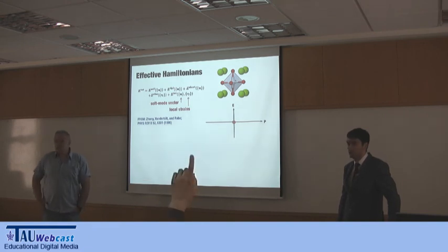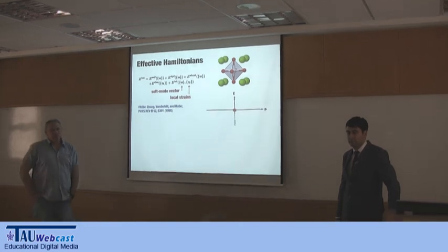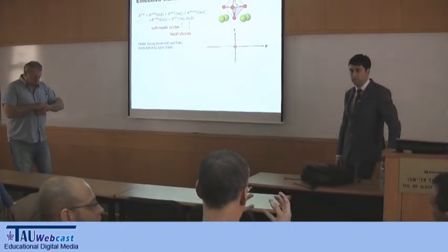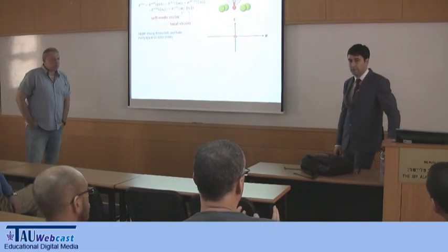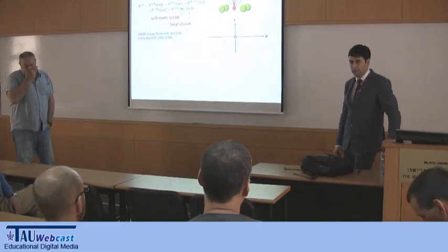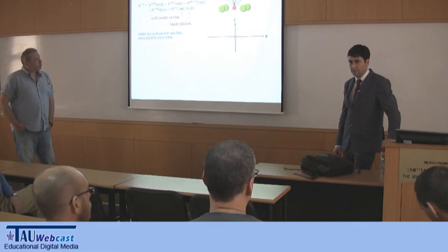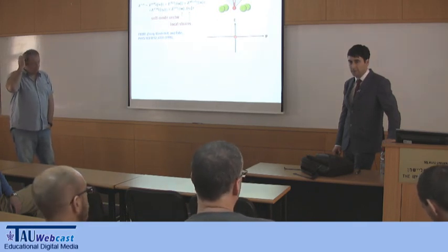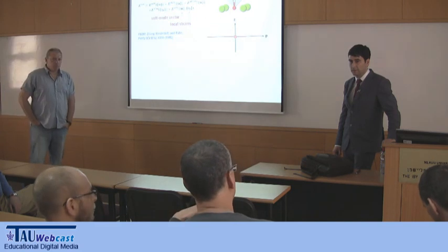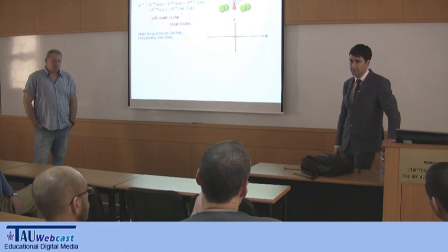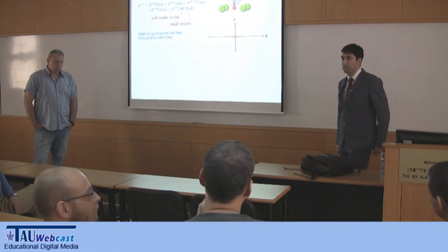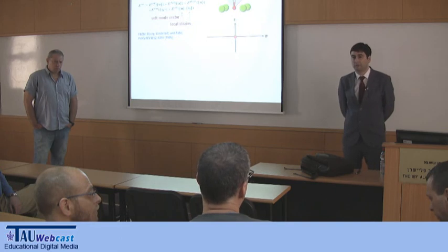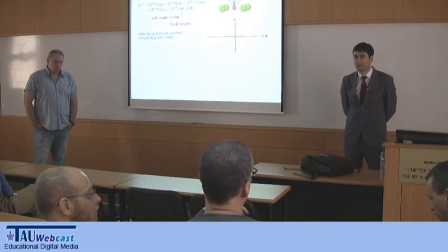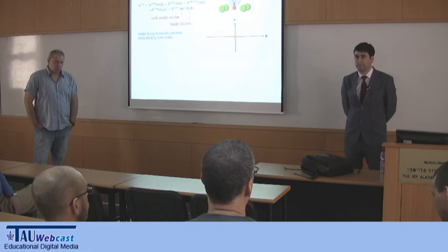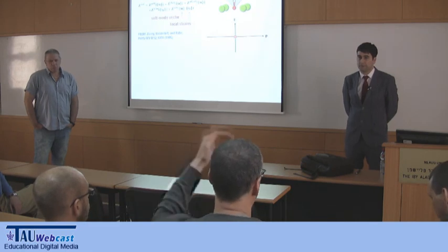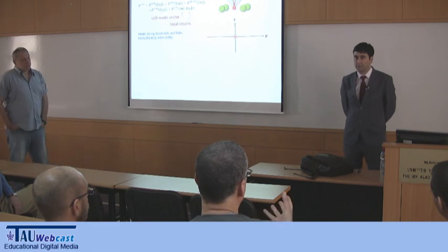More questions, please? When you showed this, there were cases where you quenched the system very quickly and it formed a different structure, and then you mentioned that this structure can be accessed at higher pressures in the experiments. You calculated the transition pressure, and it was actually a little bit lower than in experiment. My question is, why is it lower? The reason I'm asking is because I suspect that in the experiments, these transitions may occur through defects, which do not exist in the simulation. So if it was a perfect lattice in the experiment, it would be even higher. So why does the DFT miss so much?